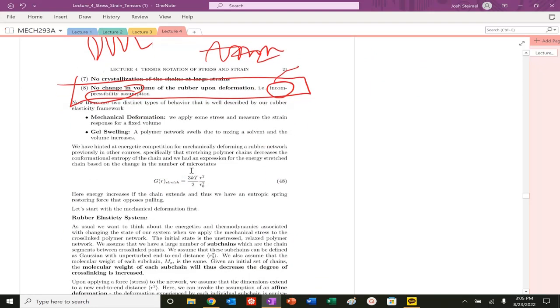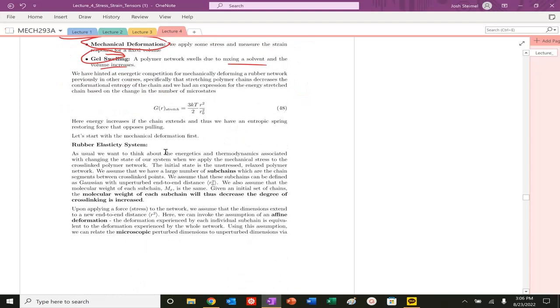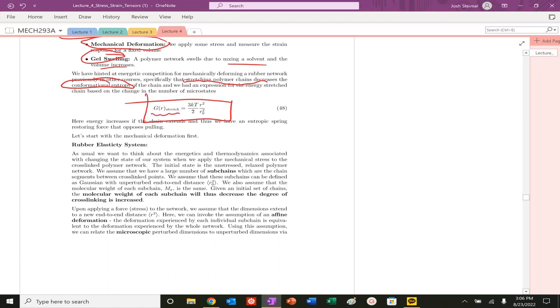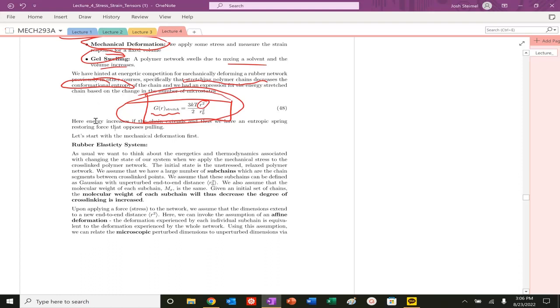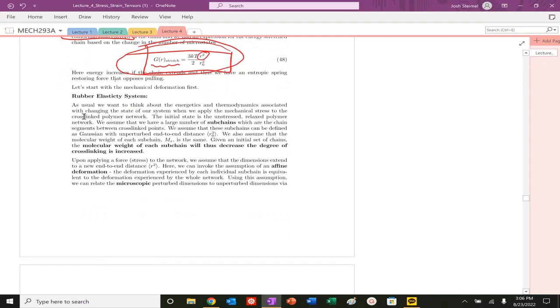So this rubber elasticity framework that we're going to talk about, it will describe mechanical deformation. It will also describe gel swelling too, when you mix a solvent with a polymer and the volume increases. Like we've hinted about previously, all of this energy, as you stretch that polymer chains, you are going to decrease the conformational entropy of your system. So you're going to change the number of microstates. So you can see here, this final expression, that the energy for stretching, as temperature increases, that energy increases. That's not good. We want energy to decrease. But you can see here, it'll change the number of microstates. This R is our end-to-end distance of our polymer chains. We're going to get into that in a second. But as you increase the size of that system, you reduce the number of microstates. You increase the energy of your system here. So that will be combated when we come back to it. So there's going to have to be some force that fights back against that. Same thing when you compress the system as well.